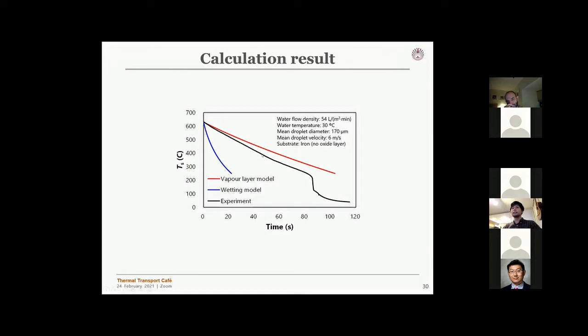So these two are basically two different extreme cases. And if I look at this figure, I can infer that in reality, as in the experimental curve here, we have two combined heat transfer mechanisms. Most of the droplet is floating on a vapor film, so it has film boiling heat transfer, but some region of the droplet may be in contact with the surface. So it may make sense that the actual cooling curve should be somewhere in between those two curves.